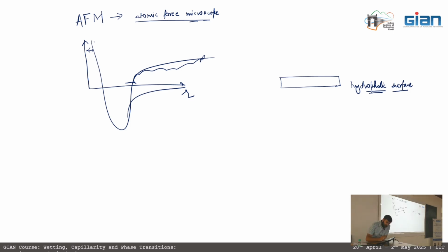So first they take a solvent or a liquid such as acetone or ethanol, and they supersaturate this with the gas whose bubbles they want to see. Let's suppose they saturate it with nitrogen gas, and then they place the substrate in this liquid for a certain time.